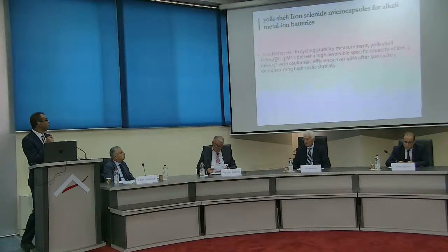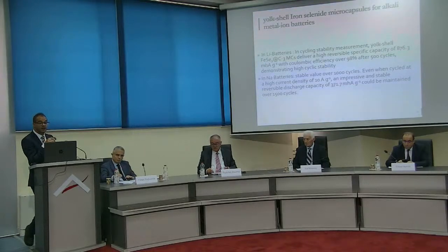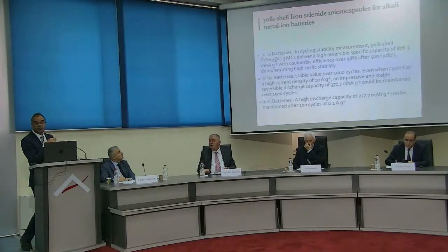But again, when we tested this material in lithium, we really achieved over 500 cycles with Coulombic efficiency over 98%, and also that's with selenides. In sodium is still performing very well, reaching a record really for that. And also potassium in particular, which is the biggest ion of all these alkali metals, could reach over 100 cycles, depending on the current rate.